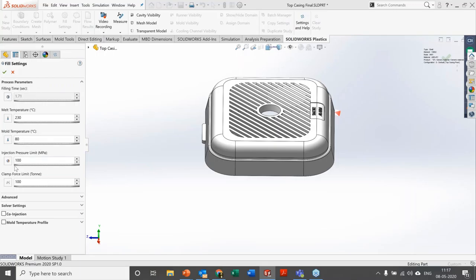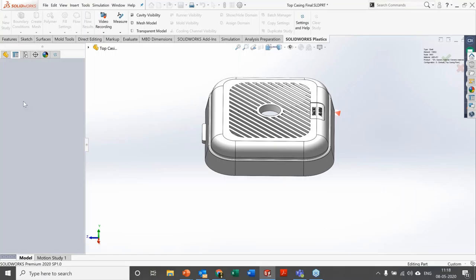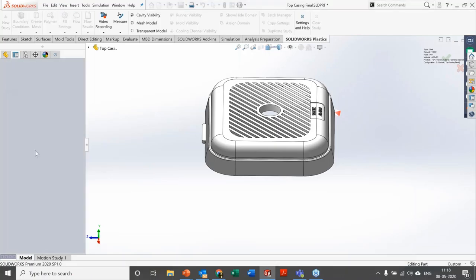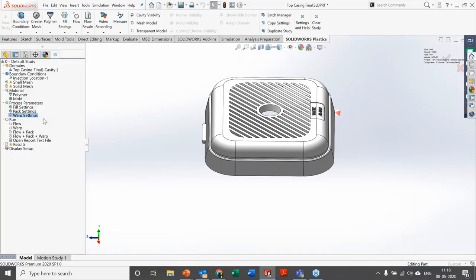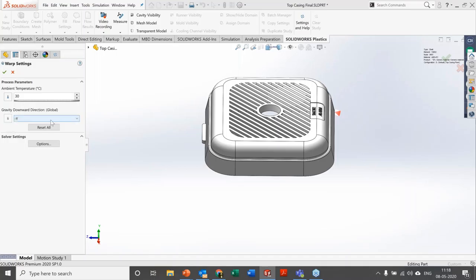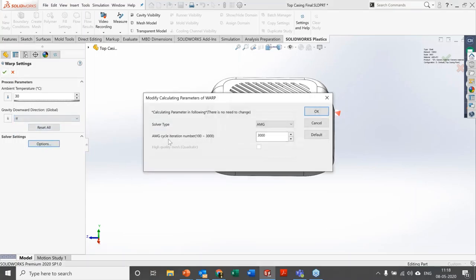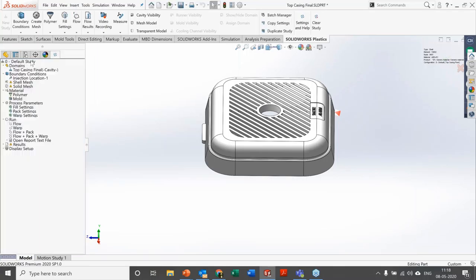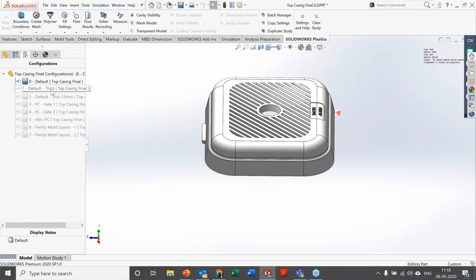Once material is selected, go to fill settings where you can see fill time, melt temperature, mold temperature, and injection pressure limit. By default these are taken from the chosen material and boundary conditions, but you can change them to experiment. Pack settings include pressure holding time and cure cooling time. Warp settings let you set mold temperature, ambient temperature, and gravity direction. In options you can set solver types and iteration numbers.